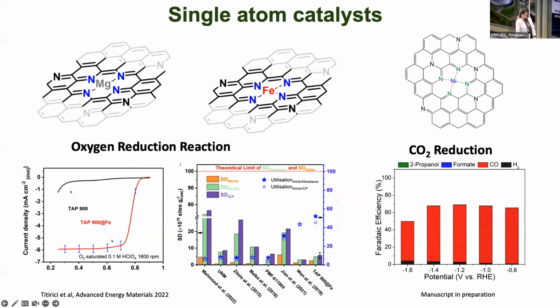So I put here just some examples. We use this iron coordinated to nitrogen in the oxygen reduction reaction. This is a very recent paper where you see that we get a very decent oxygen reduction reaction performance. But what is nice when we compare this with the literature is that we determine the number of active sites in the single atom catalyst by two methods: from Mössbauer spectroscopy and using an electrochemical technique, nitrite stripping, that reacts with and poisons the iron sites, and then you can quantify the amount of iron sites. And then we normalize this by the total number of iron sites that we determined by ICP-MS.